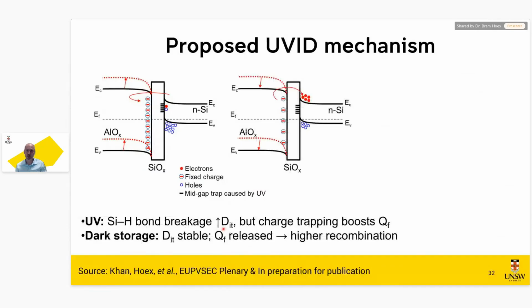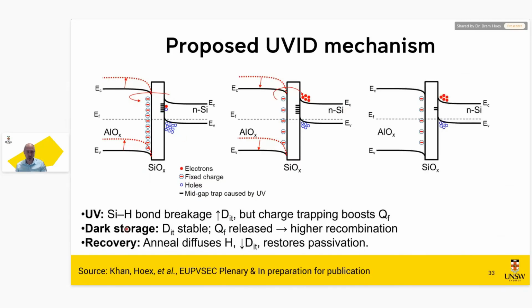In the dark, DIT remains constant. Charge that you pumped in goes back to the steady state condition, so increasing recombination. Fortunately, you can recover that. So if you anneal, you actually fix DIT. If you expose to UV, you fix the QF, so you increase the QF again. So that's our current understanding of UVID, explaining all the metastability, and this is informing the standards as well.